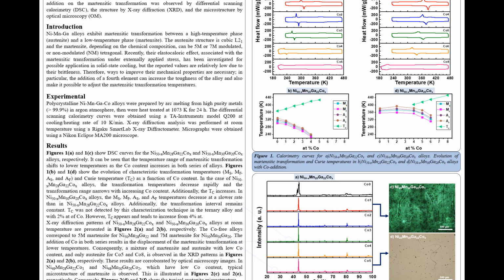Polycrystalline nickel-manganese-gallium-cobalt alloys were prepared by arc melting from high-purity metals in argon atmosphere, then were heat-treated at 1073 Kelvin for 24 hours. The differential scanning calorimetry curves were obtained using a TA Instruments model Q200 at a cooling and heating rate of 10 Kelvin per minute. X-ray diffraction analysis was performed at room temperature using a Rigaku SmartLab X-ray diffractometer. Micrographs were obtained using a Nikon Eclipse MA200 microscope.